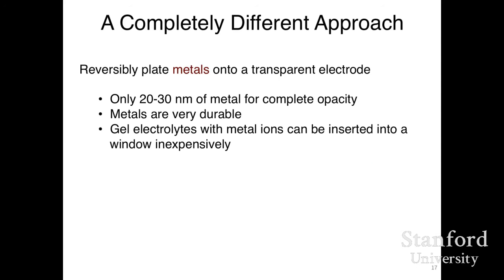So with all that in mind, we wanted to take a completely different approach. We're not completely convinced that the leading technologies out there will ever have all of the properties that are needed for the most demanding applications, like windows in homes and commercial buildings. And we thought of a totally different way, that is to use metal instead of metal oxides. It only takes about 20 to 30 nanometers of metal to completely block light. You don't need microns, just 20 to 30 nanometers. And also, metals are very durable.